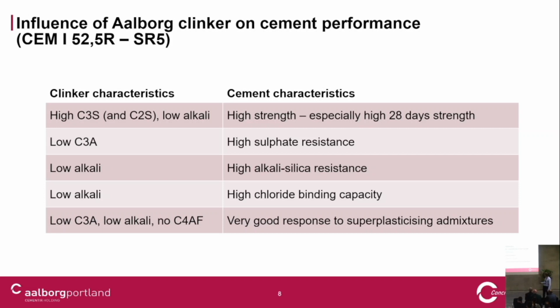Also the low alkali - well, this is maybe a small thing, but when you have a cement which is sulfate-resistant with low C3A, you normally say, okay, but that cement is not good in seawater because it will not bind chloride, since there is no aluminum to bind the chloride.